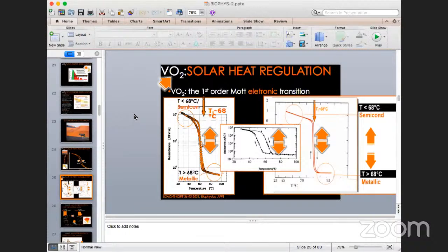And the TC decreases with the concentration of molybdenum or tungsten, but generally speaking, tungsten. Yes, it is possible. And if I may, is it then possible to, let's say, go down to 20 degrees? Yes, of course. Oh, fantastic. Yes, yes. Except that the ideal is to have 25, so as to ensure that it's room temperature, at least in non-hot countries. But it is possible, yes, by doping with tungsten.